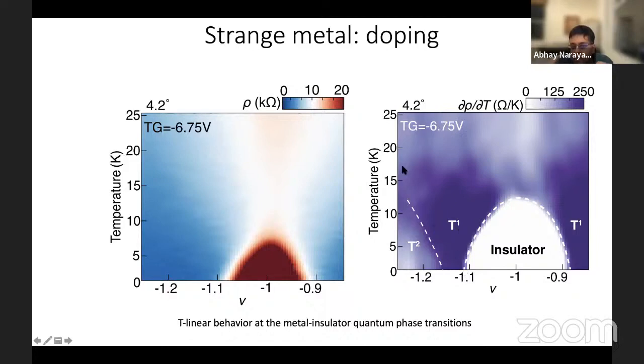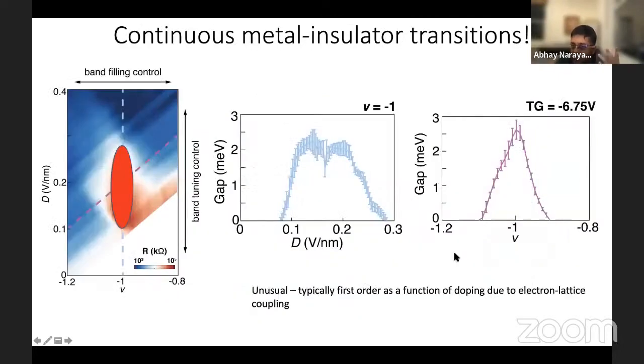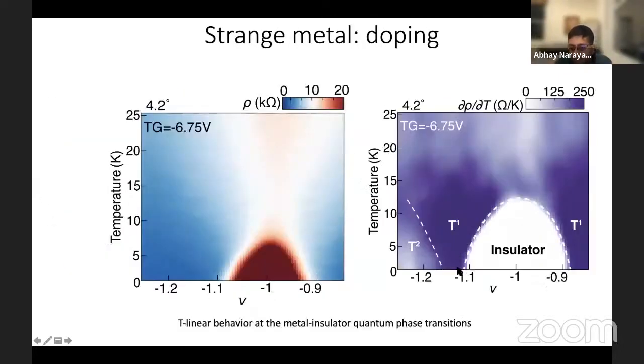And if you stare at this dρ/dT plot, you realize that close to this metal to insulator transition, this color scale is relatively uniform. And if dρ/dT is a constant, this tells you that ρ is linearly proportional to T close to this metal to insulator transition boundary.